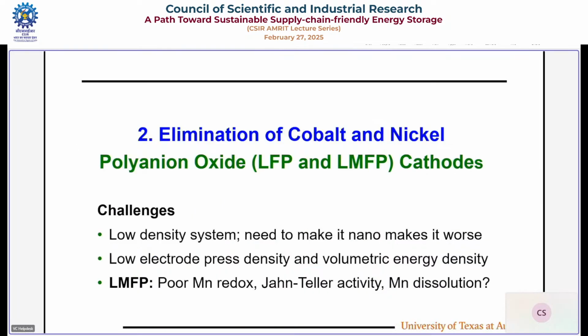Now, elimination of cobalt and nickel. This is lithium iron phosphate and lithium manganese iron phosphate. This has to be nano, otherwise it will not work. The problem here is that this is already a low-density system in terms of crystallographic density. On top of it, you make it nano, so there is a lot of porosity. So the volumetric capacity goes down.